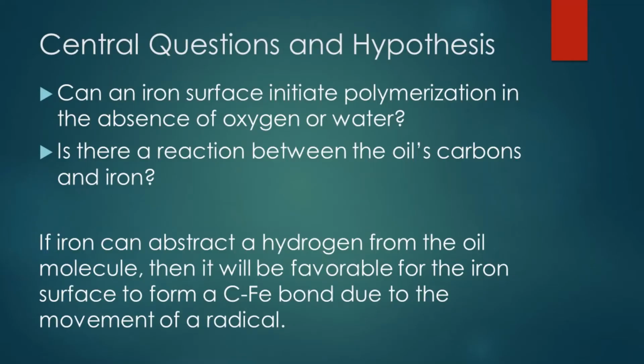There may be further interactions between iron and the oil which instigate the seasoning process in lieu of other initiators. The seasoning process is initiated by radical carbon formation, normally caused by oxygen or water abstracting a hydrogen. If it was more favorable for iron to abstract a hydrogen over absorbing the molecule, then it may be possible for the iron surface to catalyze the seasoning process by radical formation. I sought to model these systems using Psi-4 in order to determine the energy of various iron-oil interactions.